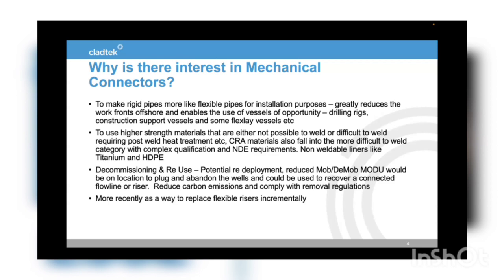But if a CRA pipe is using connectors, it doesn't know if it's clad or not. So it removes that complexity. And the other area are non-weldable liners or CRA materials, corrosion-resistant materials like titanium or even HDPE. So if you're not having heat in the field, you don't have the issues of damaging the liner through welding. And in the case of titanium, it's not technically possible to clad titanium and carbon steel with a welding process. The only way to attach those two together is explosion bonding, which is not feasible for pipe jointing.